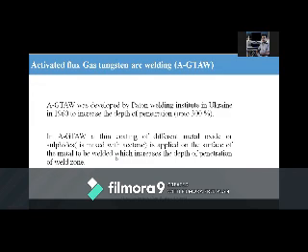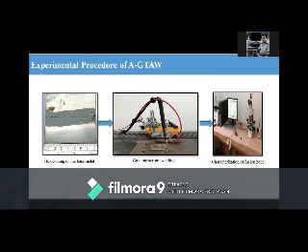As you can see here, this is the metal before welding. We have applied a thin coating on the base metal. We have to make a paint-like consistency. We use the flux with some amount of acetone, and we paste it using a brush. So this is the flux, and then we have to weld it.